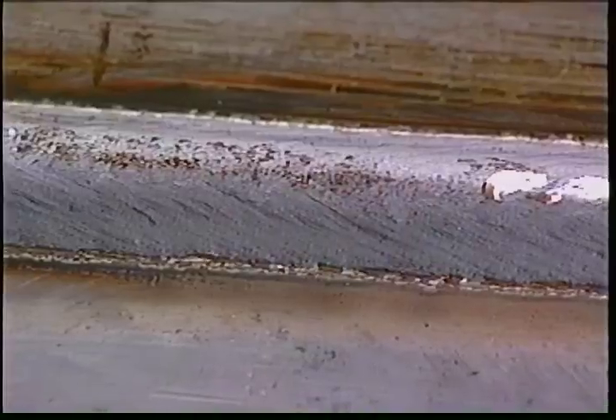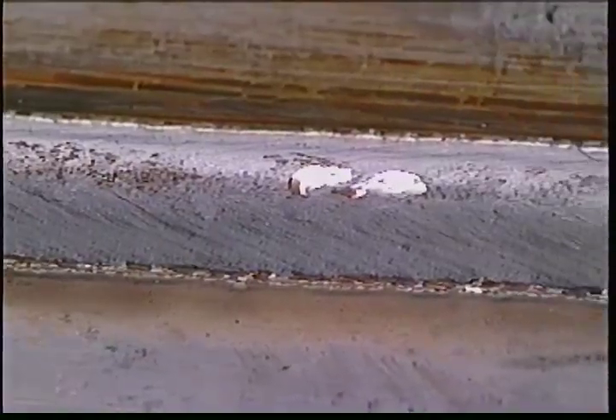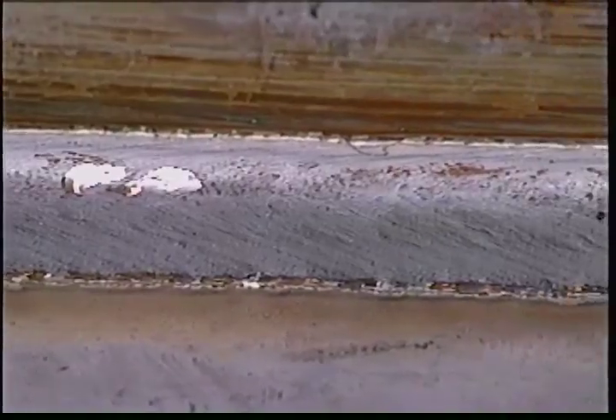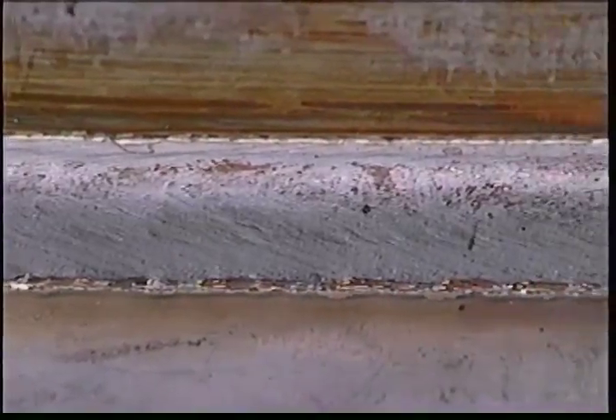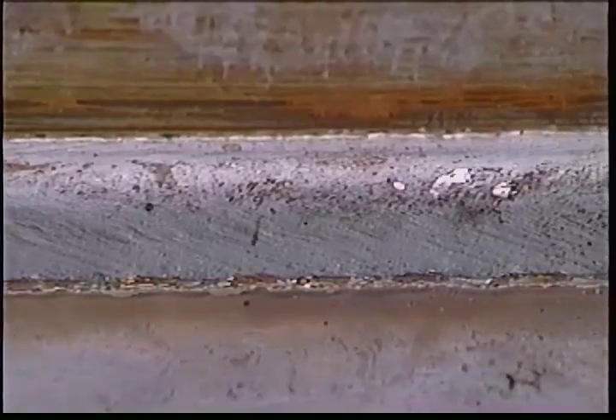High metal deposition rates are achieved as a result of the high current density. A high degree of heat in the spray arc results in a large fluid weld pool, limiting its use to the flat and horizontal positions, and then only on materials of 1/8 inch or thicker. Spray arc offers high deposition rates, use of larger diameter wires, good bead appearance, great fusion and penetration, and very